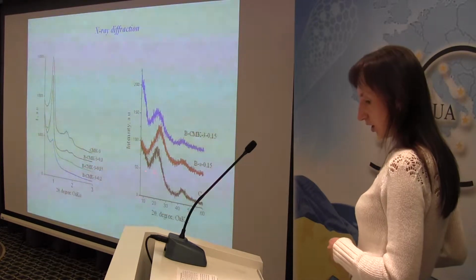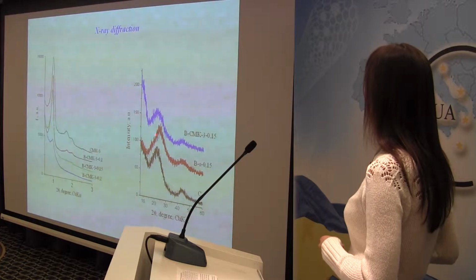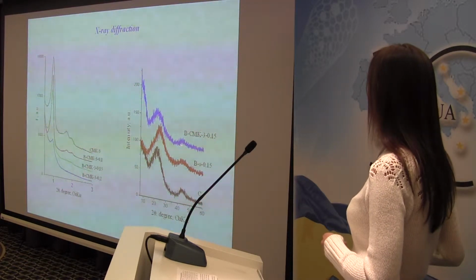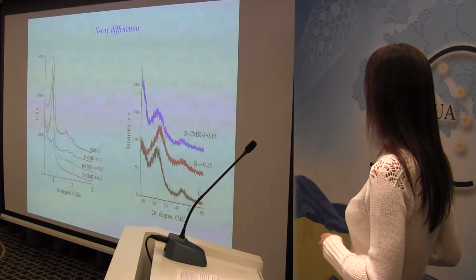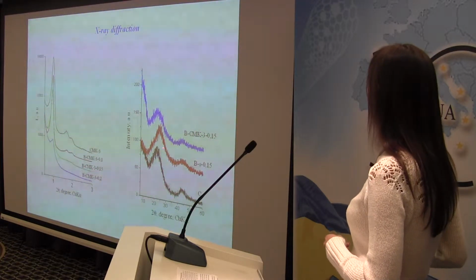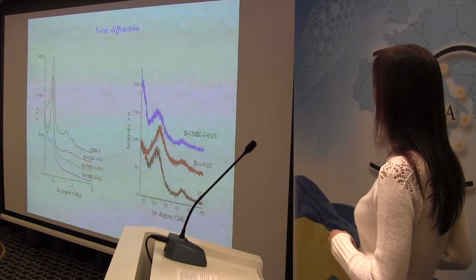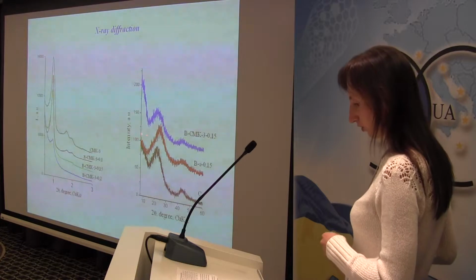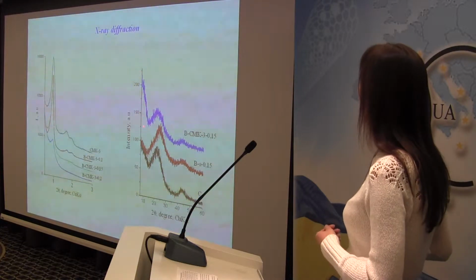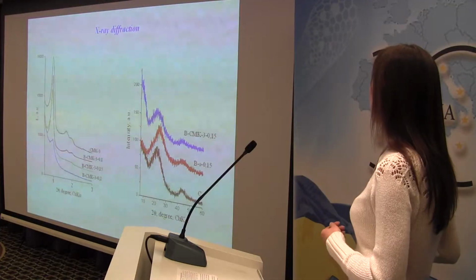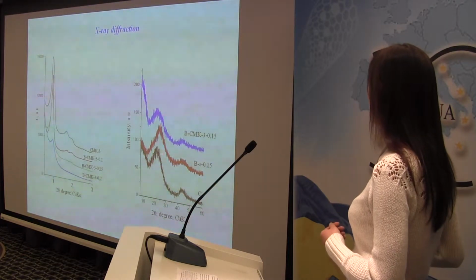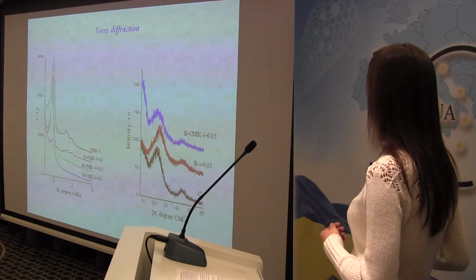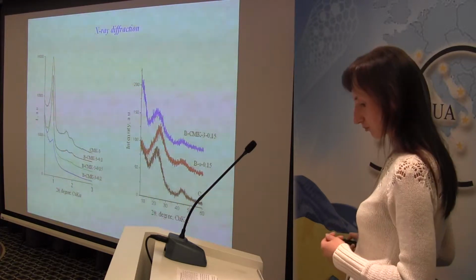At the same time, the broad low-intensity peaks at 20-26 degrees and 44 degrees testify to the predominantly amorphous nature of the framework of the obtained carbons, probably with a minor fraction of graphite-like fragments.